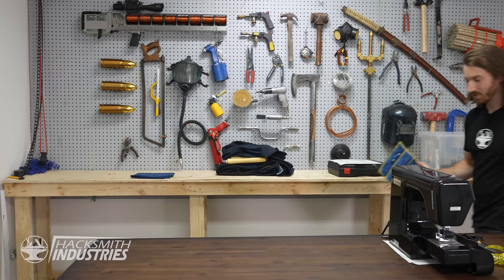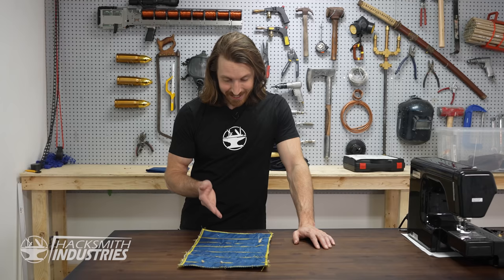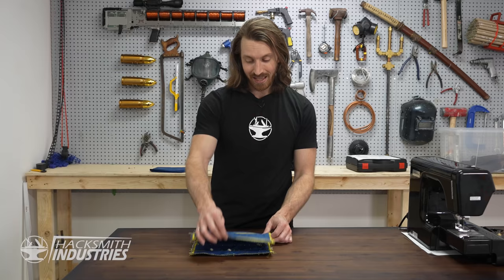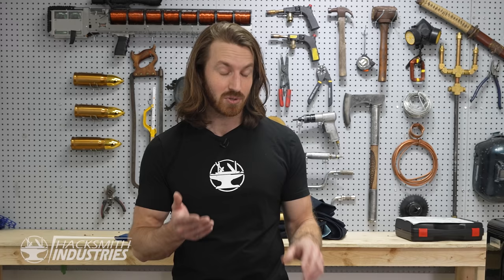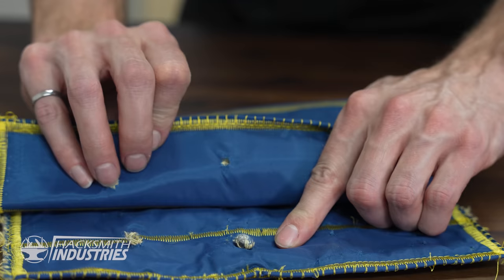All right, that was freaking cool. Not bad for my first attempt at making a bullet-resistant fabric. I mean, it stopped the shotgun pretty good, and it even stopped the 22 rounds when we doubled it up. And I think we hit the sweet spot of about 6 layers to be 22 proof, because as you can see, it actually caught the bullet here. It did go into the next layers, which you can see right there, but it was stopped.